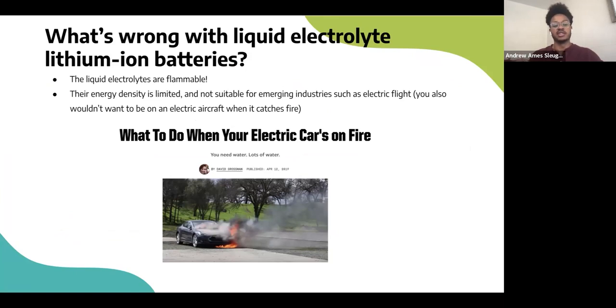is an industry that we'll have to invest in heavily in order to reduce the emissions of our current transportation sector. However, electric flight requires high power consumption, which leads to higher operating temperatures, which degrades the battery faster. And as Maddie mentioned, this will lead to a higher prevalence of unwanted side reactions. This also increases the risk of thermal runaway, which is bad for liquid electrolyte batteries because your electrolyte is flammable.